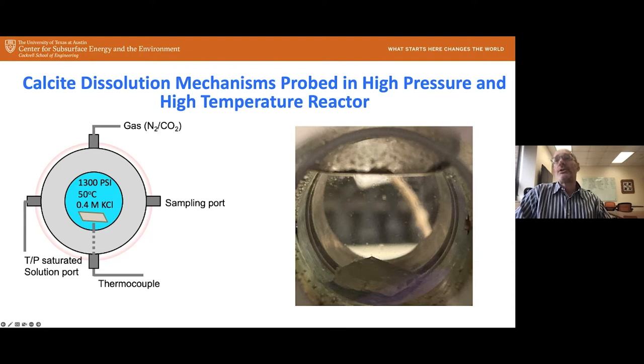We have our brine here, which you can see. In this case, it's saturated with supercritical CO2, and overlying that is supercritical CO2 in the pure phase, so no liquid or brine at the top. We allow this to age for a certain time period, and then we can sample the fluid during the experiment. We have a port here with a pressure release valve to capture that fluid as a function of time. At the end of the experiment, we can take that sample out and analyze it.